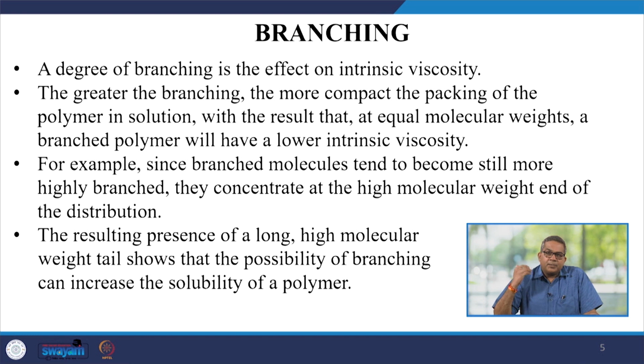Now, the greater the branching, the more compact is the packing of the polymer in solution. It is like this: we have different chains, and if the branching is on, then a more compact structure would be there, at equal molecular weights. A branched polymer will have a lower intrinsic viscosity. So, when we determine the molecular weight distribution through the viscometer, it plays a vital role.